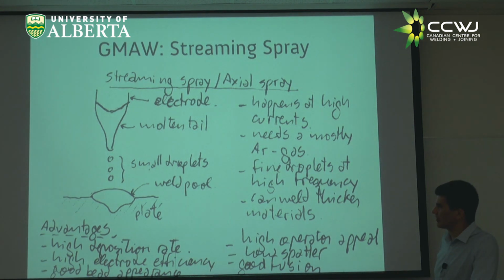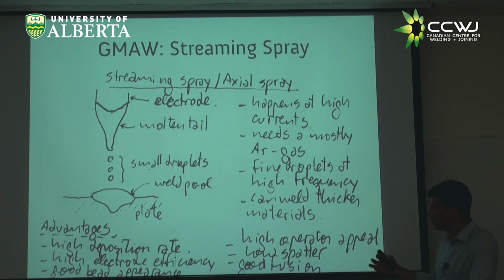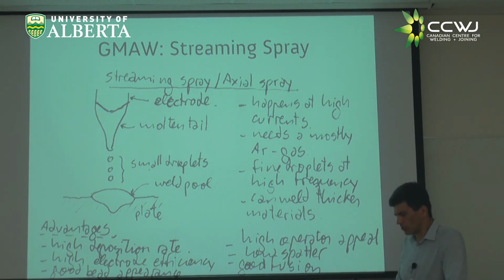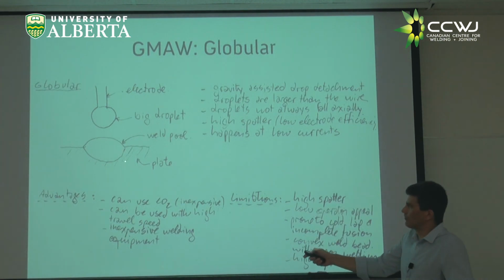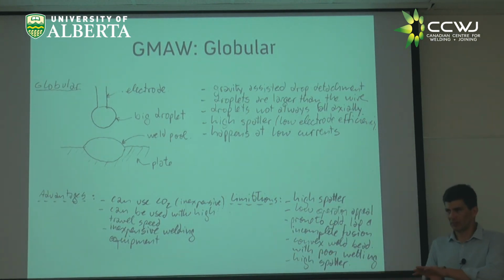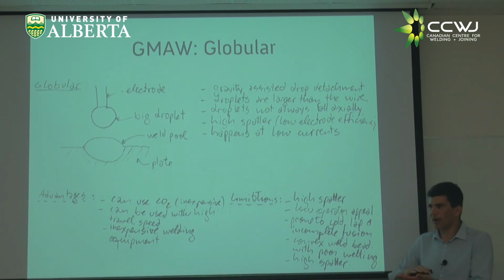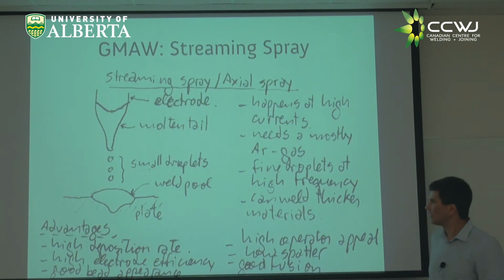Good for welding thick materials without causing much problems. High deposition rate, good electrode efficiency, so low spatter, good weld appearance. The operators like it, right? It tends to be one process that would give you good fusion. Sometimes the big droplets here would fall, but they don't really melt the sidewall, the V-groove, and you have the effect that is called lack of fusion that shows up in X-rays. You don't see it with your eyes because you see the cap passes only. Okay, so it's 3:20. I'm going to stop here and pick up on this on Tuesday.